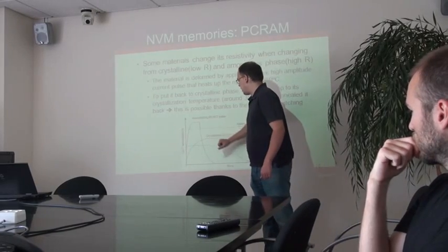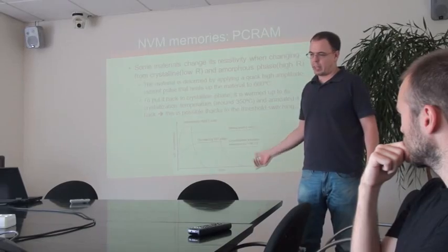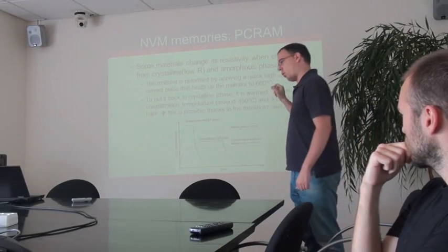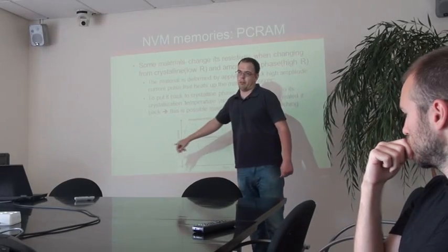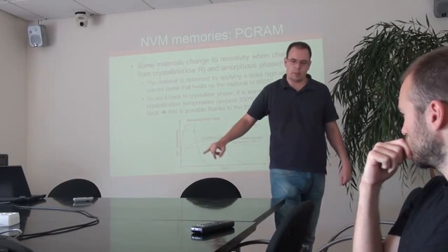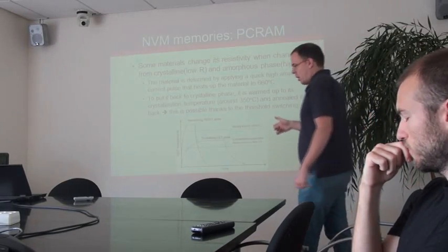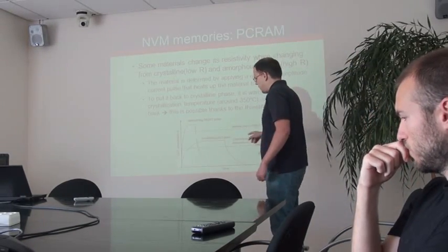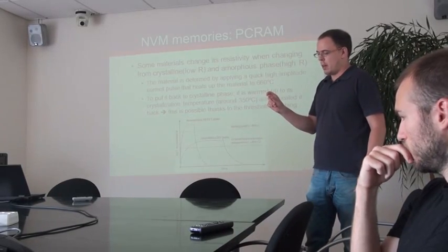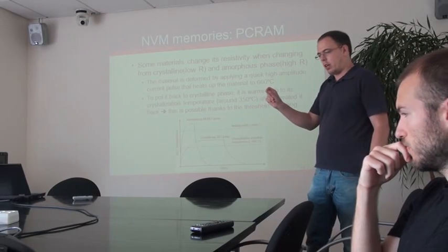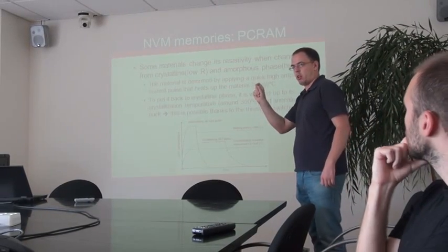If we are in a crystalline state, amorphous state, and we want to make it crystalline, then we apply a pulse, this one. But hold on, if the conductivity is null, how can we inject current? Okay, the key to these materials is that they present threshold switching, in which if you apply the voltage up to a threshold, this material presents a sudden pulse of intensity.